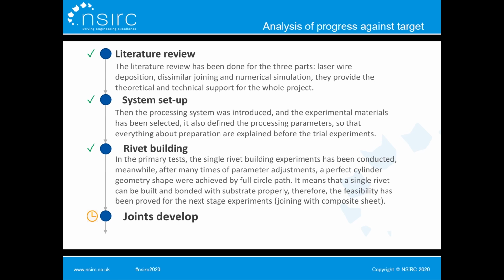They all focused on laser metal wire cylinder deposition, which had a feasibility study to deposit a proper cylinder. Then the parameter improvements to significantly reduce the processing time. What's more, a new thermal analysis numerical model has been developed to calibrate the experimental result.